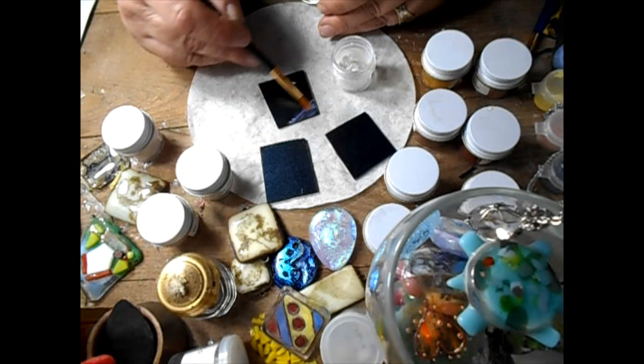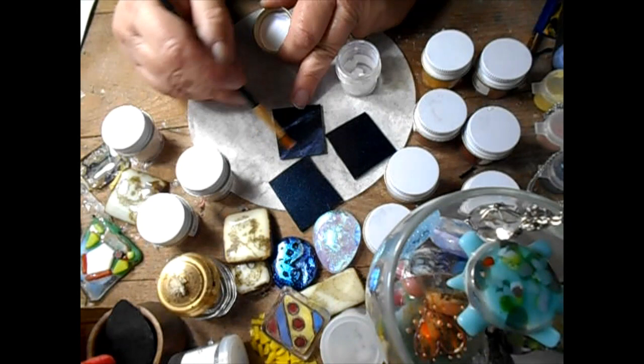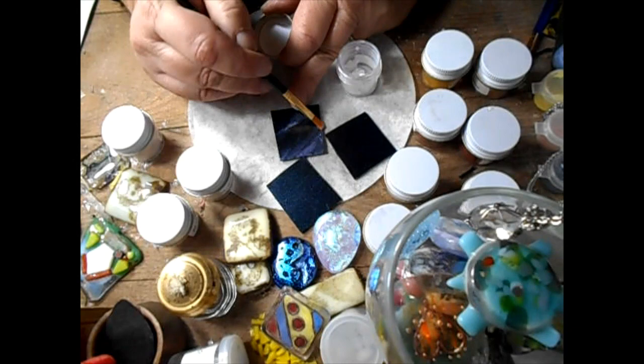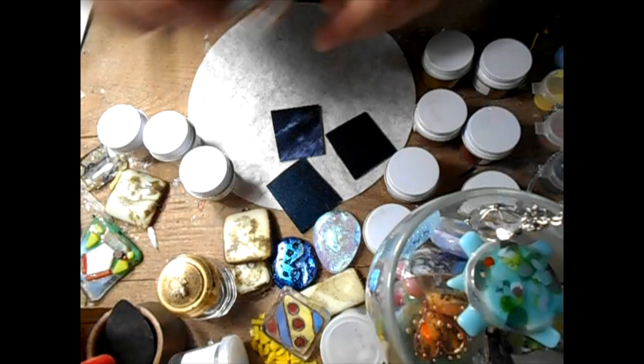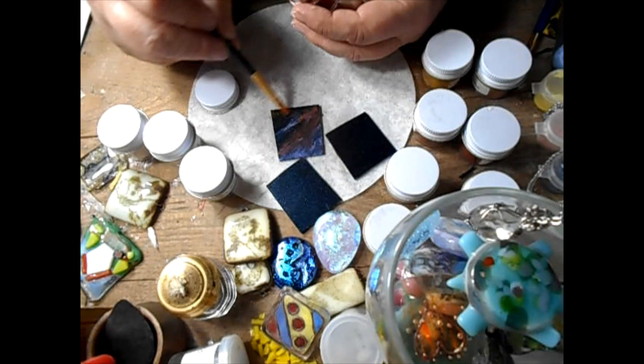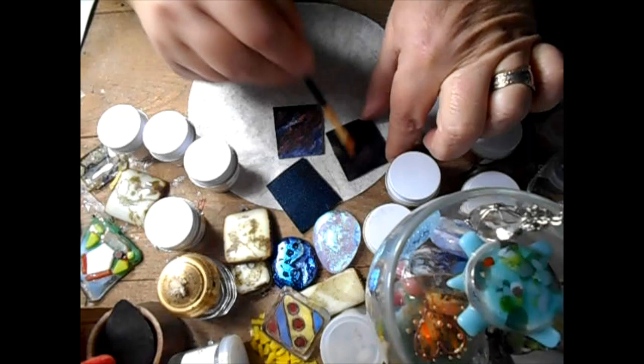I'm just going to swirl a little bit on here. With mica powders, more is not necessarily better. Mica does not melt-fuse into the glass — it'll fuse onto the glass, but only exactly the particles that are touching the surface. Anything extra is going to wipe off, and it doesn't matter how much you put on there, it's not going to make it thicker or heavier. It's going to come off after it's fired, so you don't need much — just a little bit. Spread it around. This one here is number six orange, and I'll mix that in with the blue — that's where we're kind of faking the iridescence, adding different colors.